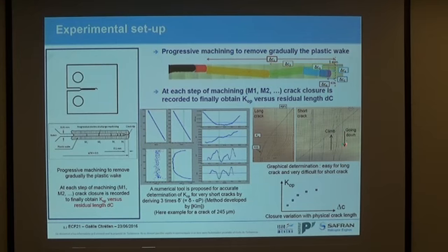The transition is less visible. So I developed a tool proposed here, using the method proposed by Kim, which consists in calculating the delta prime, which is here, for example, and deriving it 3 times in order to find a minimum and to have a more accurate determination of the K opening.